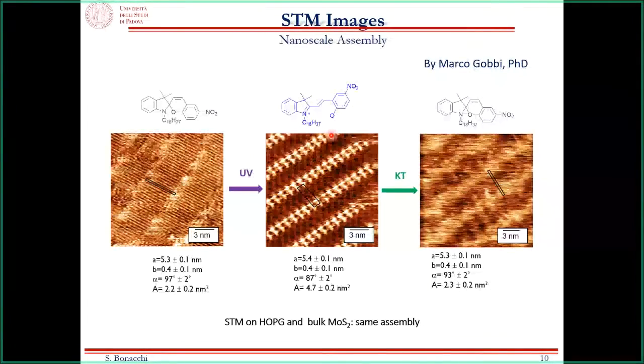We also perform STM images to observe how this molecule assembles on top of graphene as well as on top of MoS2. And as you can see here, we observe not only the assembly of this spiropyran, the closed form, on top of graphene, but also the possibility to irradiate in situ, so to shed UV light on top of this dry film and observe the modification of the assembly on top of graphene by means of STM, and then back with the thermal relaxation to the original form. So this was actually one of the first proofs of the possibility to work with this highly ordered lattice structure on top of 2D material, to observe their ordered film, and also to tune their assembly in situ by playing with light.